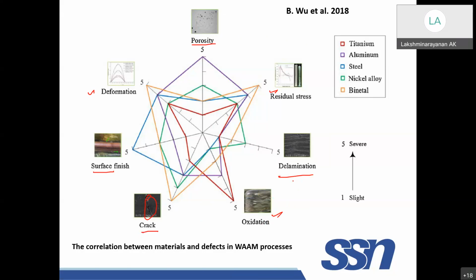The number is given here: maximum is 5 and minimum is 1. You can see titanium, aluminium, steel, different metals here. Porosity is the biggest problem in the case of aluminum. See the color here. Porosity is the biggest issue in aluminium. When you compare these four materials, or you have bimetal here, if you see the bimetal, the residual stress is huge.